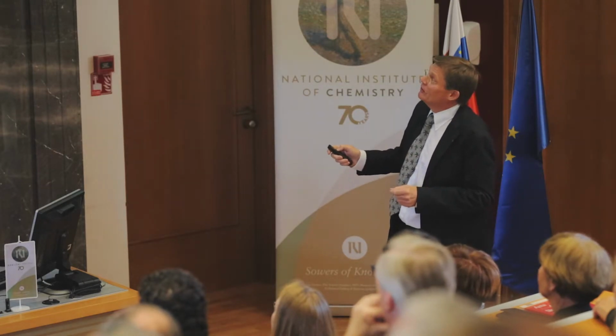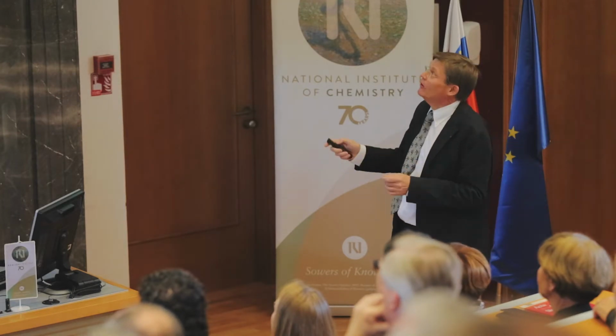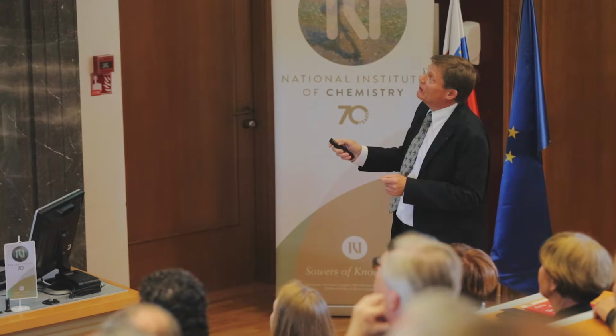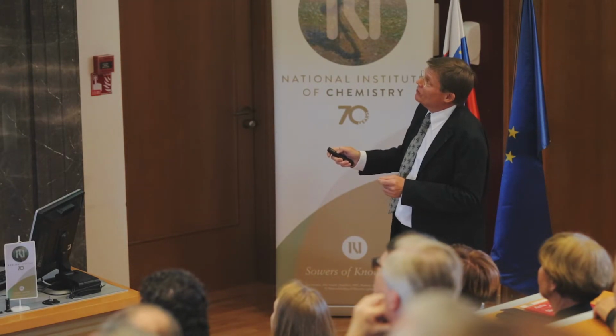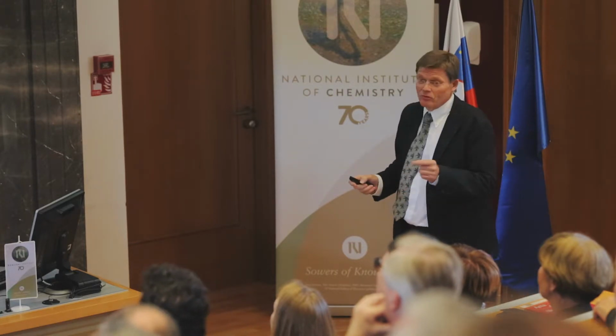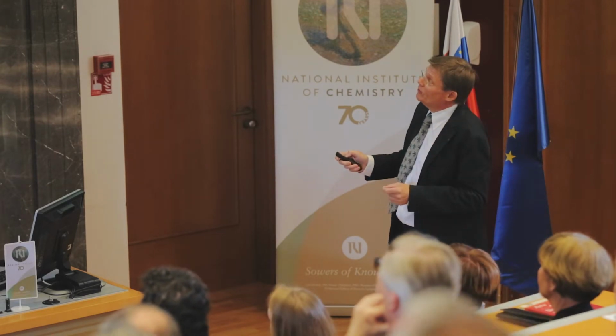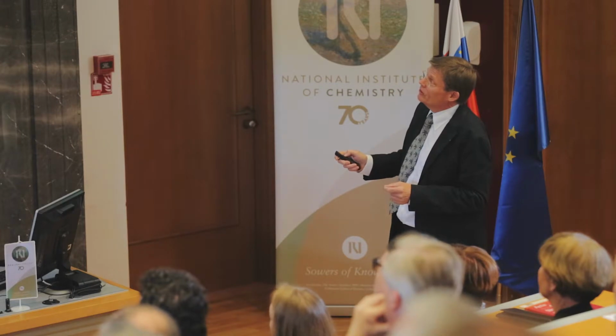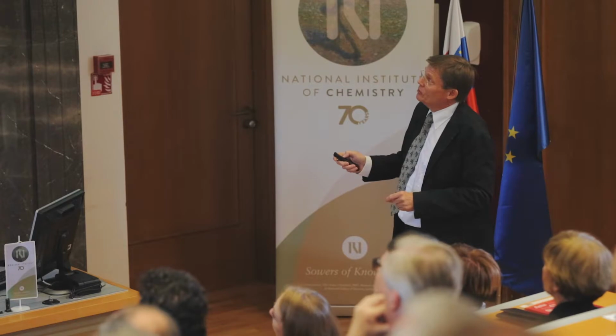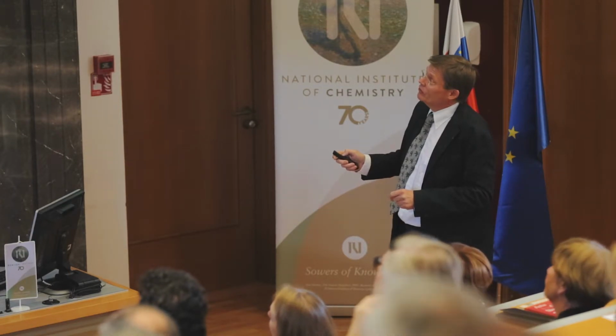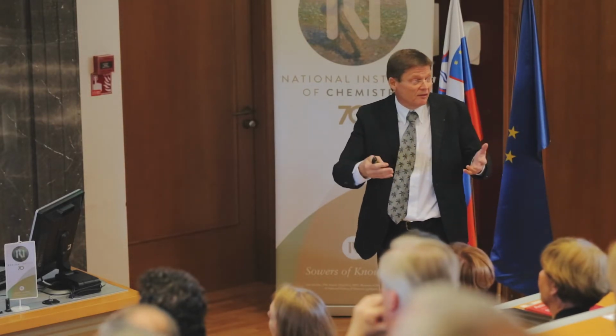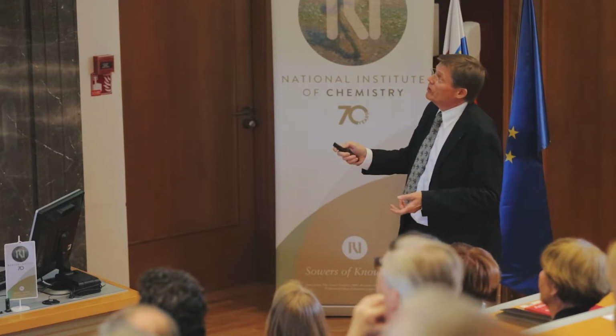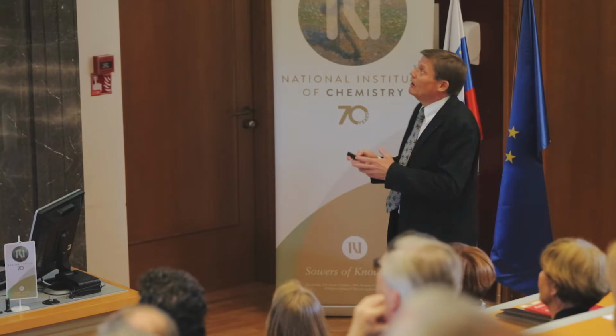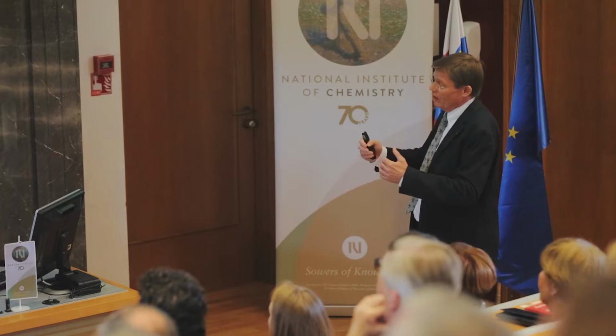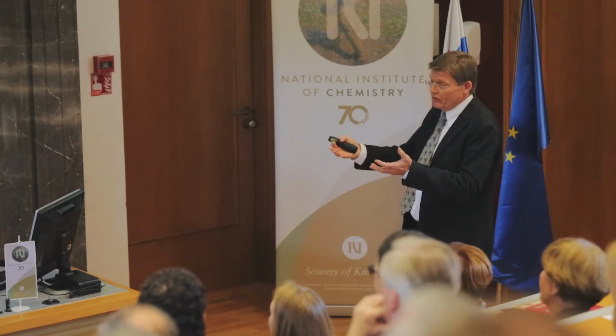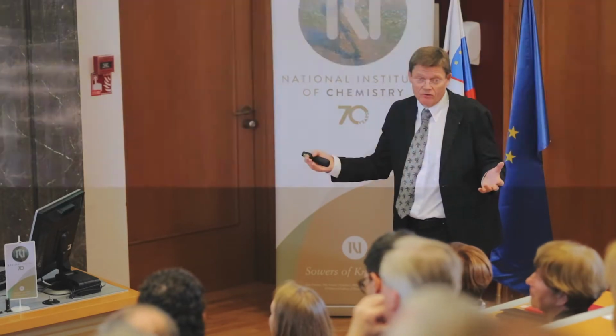However it is, you can define a characteristic thermodynamic function which depends on internal energy, entropy, and so on. This is interesting because any of the terms that appear in that variation refer to a capacitance. You see, the volume is the first derivative of this function, which characterizes the statistical ensemble, with respect to pressure. The second derivative would be the derivative of the volume with regard to pressure. This is a compressibility, a mechanical capacitance. In the same way, this part gives a thermal capacitance, and this term gives you the chemical capacitance. It describes how much particle number varies when you change the chemical potential, which is the oxygen partial pressure that is around.